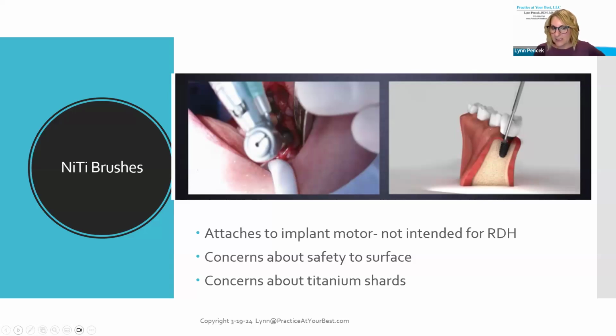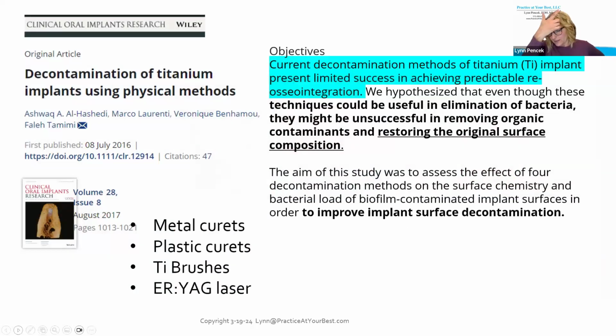But the thought here is, how do you remove the outermost layer of the implant surface? This is a study that compared decontaminating the titanium implants using metal curettes, plastic curettes, titanium brushes, and a laser. The study resulted in the most improved surface decontamination by using the titanium brushes and the laser together. Guess what?